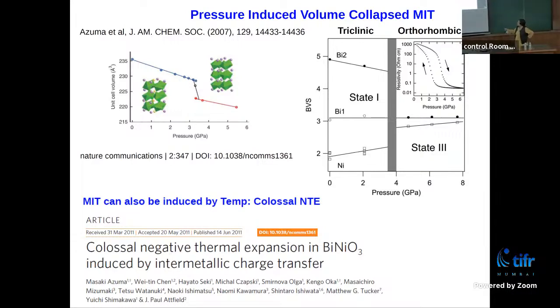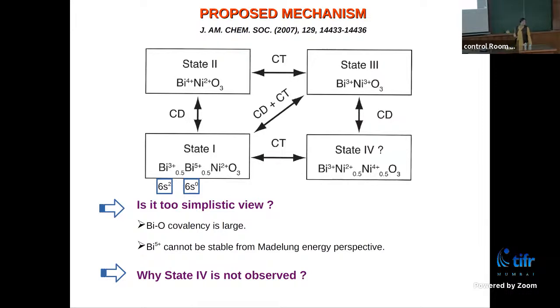This got some attention because they found such an insulator to metal transition can also be driven by temperature. You would expect by putting temperature your system will expand, but here it collapses. So it's a negative thermal expansion. And they got some patents and so on out of it. So this is their proposed mechanism.